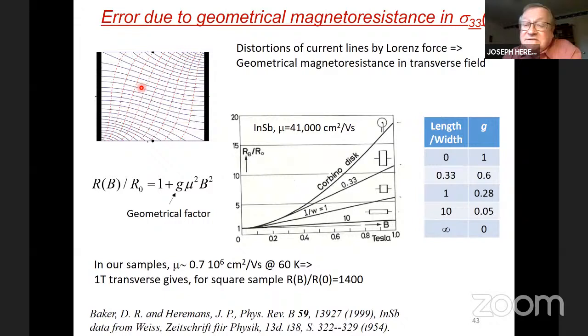And now we have something I already alluded to before, which is the error due to the geometrical magnetoresistance. So the distortion of the current lines. This is very old. This was identified in 1954. And here is a measurement on indium antimonide of the geometrical magnetoresistance due to distortion of current lines on Corbino disks and on samples with length to width ratios 0.3, 1, 10, and so on. And you see that you have a geometrical effect that scales as 1 plus a geometrical factor times mu squared B squared. I give you these geometrical factors in this little plot here as a function of length to width ratio, so for a square sample, 0.28 would be the prefactor you put here.